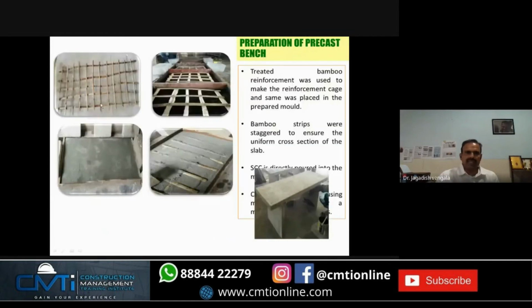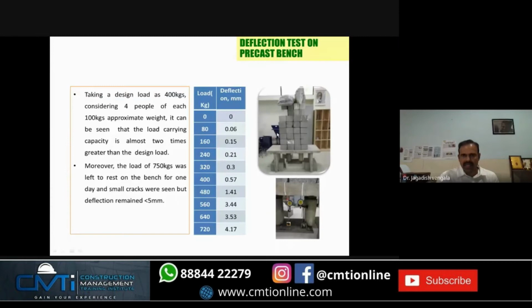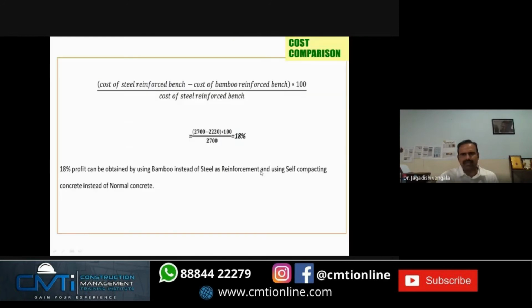Then we tied and made the reinforcement, placed it in the mold, poured the SCC and made the bench. You can see the bench. And then we did the deflection test for these benches. It comes within the limits because if you take 4 people, the load is 400 kgs, but we have gone up to 720 kgs. Over a period of time, deflection is minute, up to 4 mm. Anyway, that never happens.